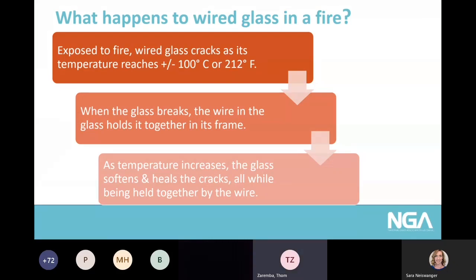Why is it a good fire-rated material? It's a good fire-rated material because when it's exposed to fire at about the first 100 degrees centigrade, or a couple hundred degrees Fahrenheit, the glass, the annealed glass, cracks. But at the same time, the wire embedded in the glass holds the glass together in its frame. As the temperature increases beyond 100 degrees centigrade, the glass actually softens and begins to heal all the cracks that were created initially at the 100 degree centigrade mark. So it actually seals itself in a way that will prevent even smoke from penetrating it, or hot gases, and certainly flames. Next.